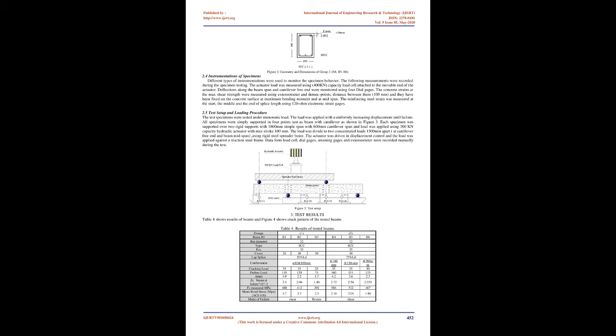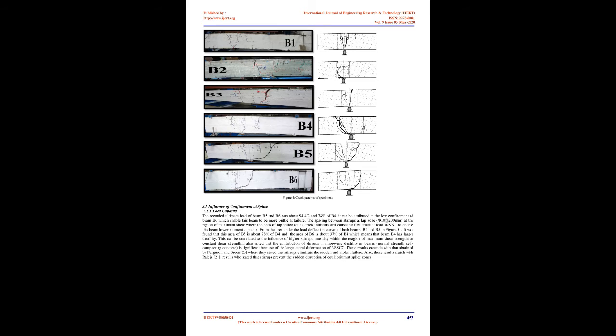The SCC beam specimens had generally longer cracks than the beams produced from NVC, regardless of the reinforcing bar diameter. The project of Cattaneo and Rosati included testing of 27 pull-out specimens containing 1 embedded reinforcement bar. The variables were reinforcement bar diameter, stirrup existence and confinement. 2 types of tests were done: unconfined and confined pull-out.